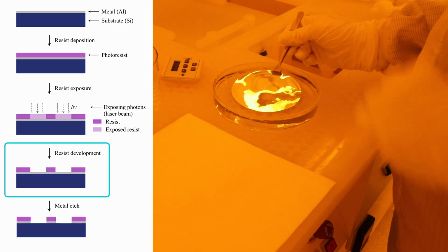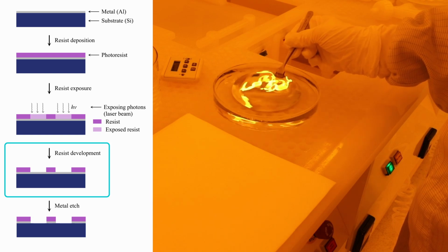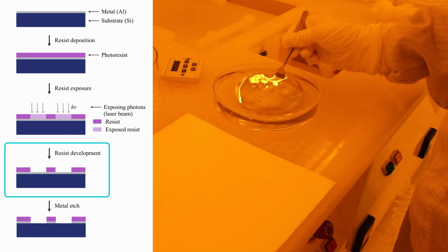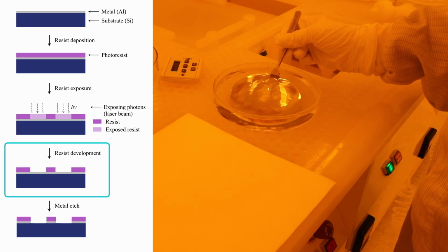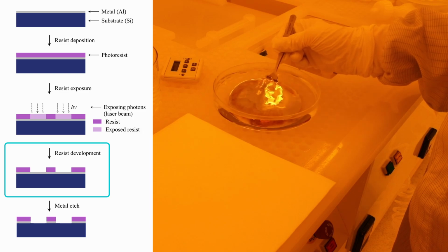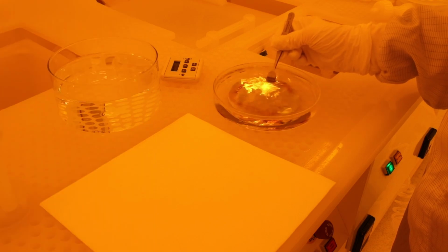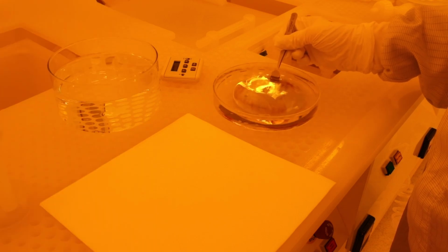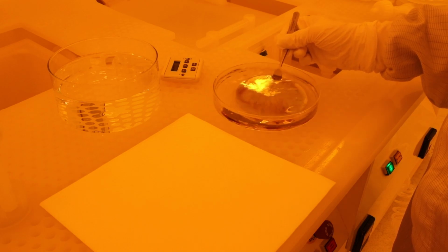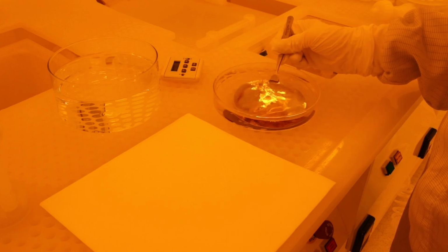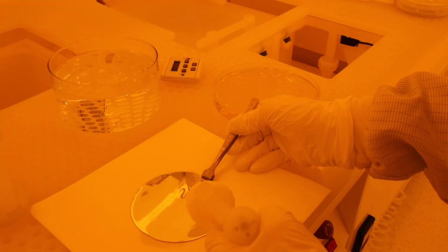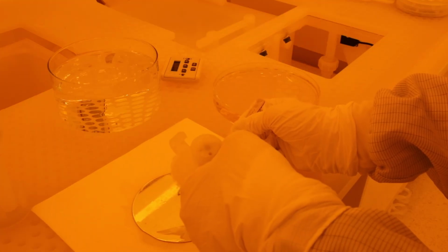Now the design has been written into the resist, but we can't actually see it until we develop the pattern in the developer. If you look closely towards the outer edges of the wafer, you should start seeing a color change as the resist dissolves there, and soon we should also start seeing traces of our qubit chips appearing in the center of the wafer. Once we are done with the development, we can stop the chemical reaction in a beaker of water and then dry the wafer under a stream of nitrogen gas.